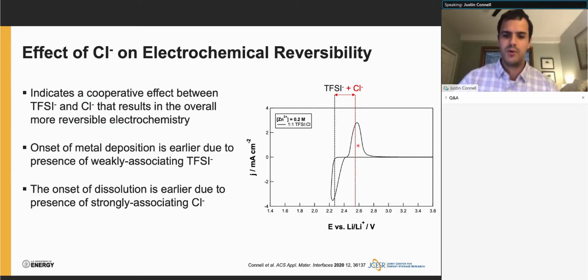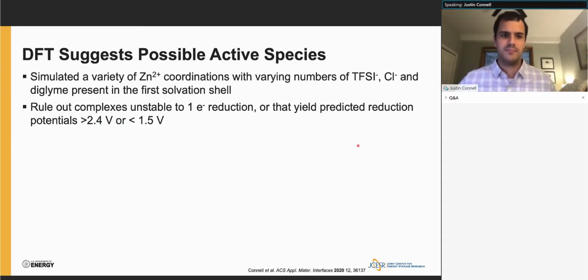And so to determine whether this effect is reasonable, we turn to density functional theory to investigate some potential active species that might be leading to this behavior. And so what we did is simulate a variety of different zinc coordinations with varying numbers of TFSI anions, chloride anions, and diglyme solvent molecules in the first solvation shell. And basically, in order to down select, we rule out any complexes that were either unstable to one electron reduction or that yielded reduction potentials outside of the window where we see any evidence of zinc metal deposition in our voltammetry. And what we find is several stable complexes, and I'll highlight a couple of them here.